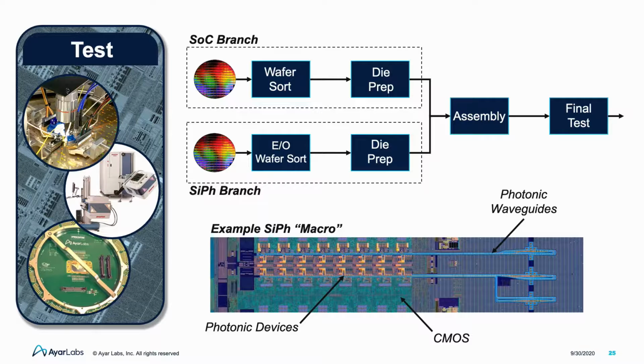Since TeraPHY is monolithically integrated, the die requires wafer sort testing that is similar to other highly integrated VLSI products. However, in addition, the wafer prober and probe card need to enable optical fibers to be aligned to the grating couplers. This allows photonic transceivers to be tested, improving test coverage, and thereby reducing test escapes. Therein is the challenge. As a very complex CMOS device, the die requires hundreds of probe pads, ideally greater than 300, which have to share the same space with up to 24 optical fibers.